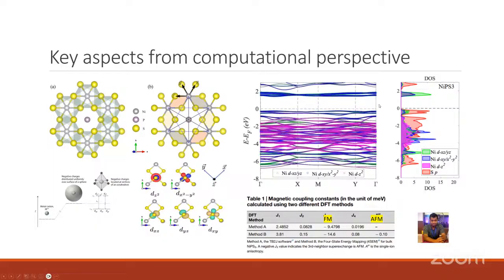So I would like to say that as long as the phosphorus p orbitals' density of states and electronic bands stay pretty far from the Fermi surface, which means the electrons of the phosphorus sites are really stabilized locally, it's relatively safe to neglect the phosphorus p orbitals' contribution and consider those electron orbitals near the Fermi surface within a finite energy window.